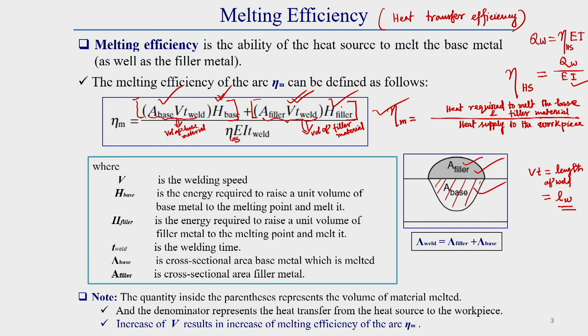Once we multiply with this energy required per unit volume of filler material, then we get the total energy required in case of filler material to raise the temperature from room temperature to melting point temperature. So, this we can easily find out. And what is this denominator? This represents whatever heat is supplied from the arc to the workpiece, that we can easily calculate